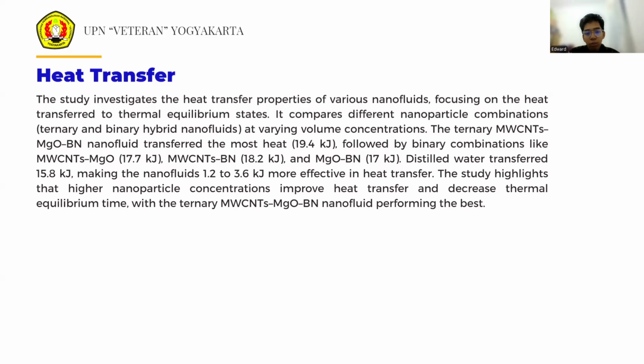In comparison, distilled water transferred 15.8 kilojoules of heat, making the nanofluids superior in heat transfer by 1.2 to 3.6 kilojoules. The study emphasized the increased heat transfer with higher volume concentration of nanoparticles, as shown in figure 15, where the thermal equilibrium time decreased with increasing volume concentration, indicating enhanced thermal conductivity overall. The ternary MWCNT, MgO, and boron nanofluid exhibits the best thermal properties, including heat transfer and thermal equilibrium time, compared to the other nanofluids.